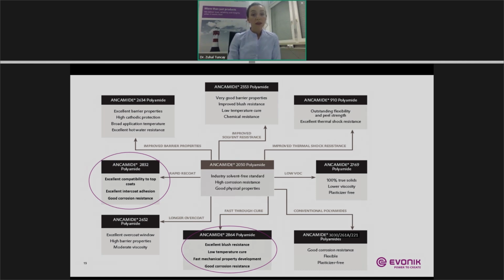2769 is a 100% true solid polyamide without any additional plasticizer and exhibits very low viscosity. This allows for formulation of solvent-free or high solid. 910 has a very high flexibility and excellent thermal shock resistance, which makes it an ideal product for electronic potting and encapsulations.